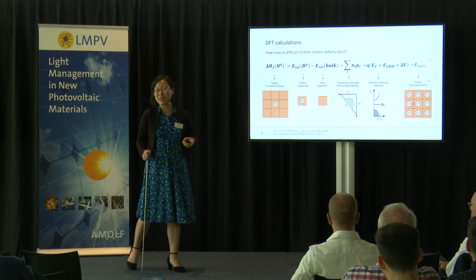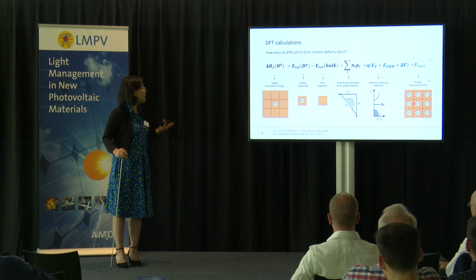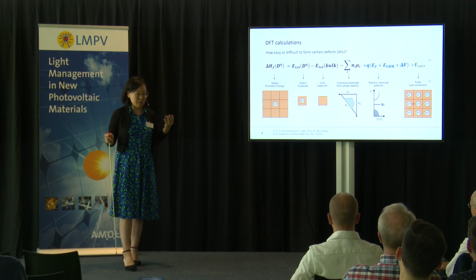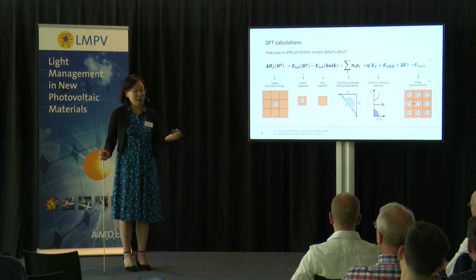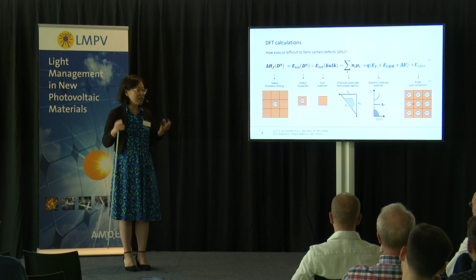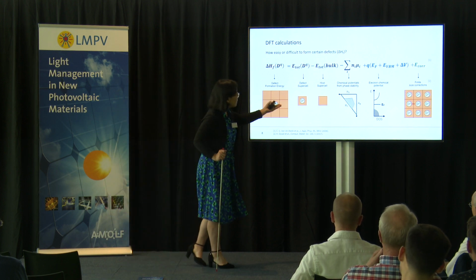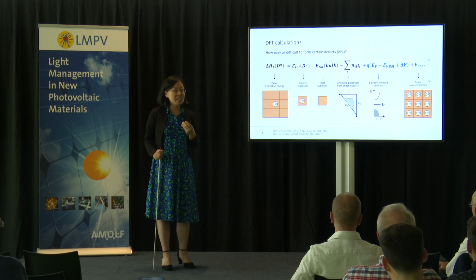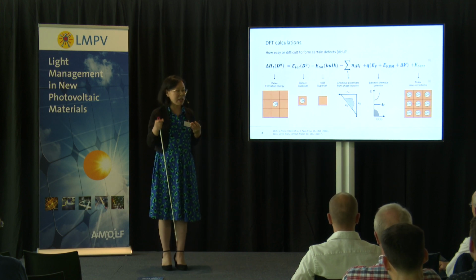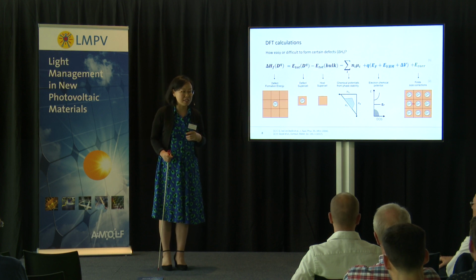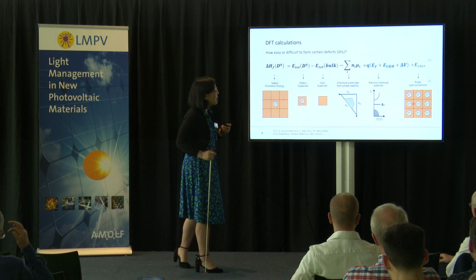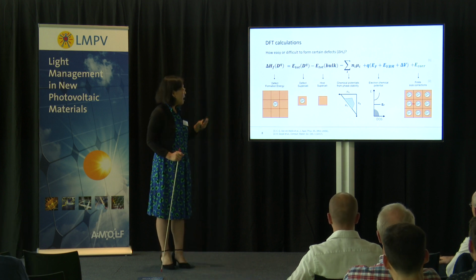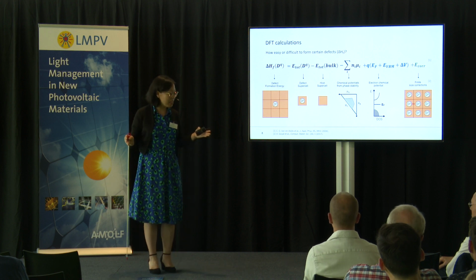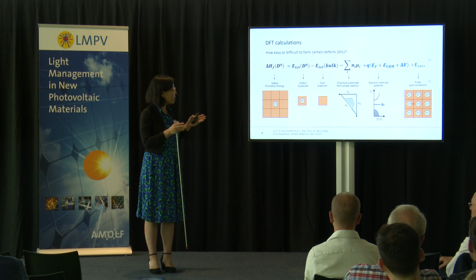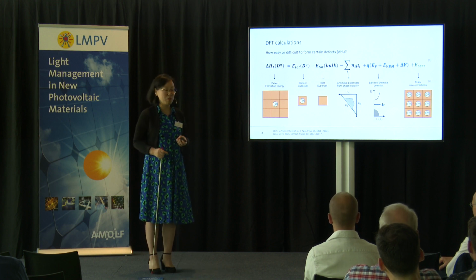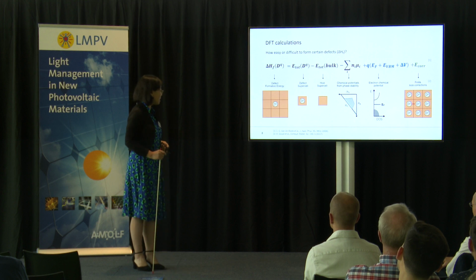Don't be scared by this equation. Basically, what we want to tell is that to calculate the defect formation energy, we calculate the total energy of the perfect lattice and the defective lattice, and then we compare the difference, taking into account the defect and chemical potential. Because this type of material is actually ionic, that means when we take the defect out or put a defect in, we also introduce extra charges. So we also make sure to correct the electron chemical potential. And of course in DFT we do our best to simulate a realistic cell, but after all the cell is still small, and we make sure we do some corrections to do our best to get an accurate result.